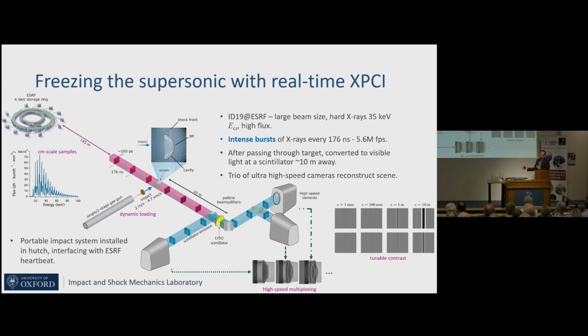It's happening so quickly. If we want to excise the information of interest about how that cavity is collapsing, we need to get as much time resolution as possible. We need as many frames of that as possible. So what we do is we go to a synchrotron, and we ask for packets of light. And these packets of light are X-rays. They're very hard, which means that they'll transmit through these materials. And we take advantage of the fact that they can deliver X-rays about every 200 nanoseconds, right? So they're very tightly spaced. So it's quite a few X-rays. And they're so short-lived that effectively they freeze the dynamics in their path. It's a still shot of that image. Okay?